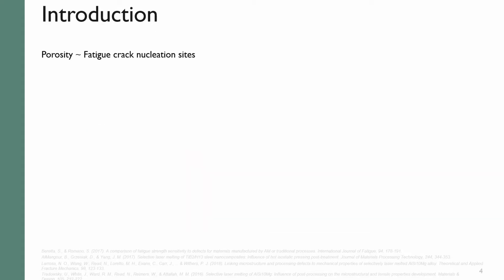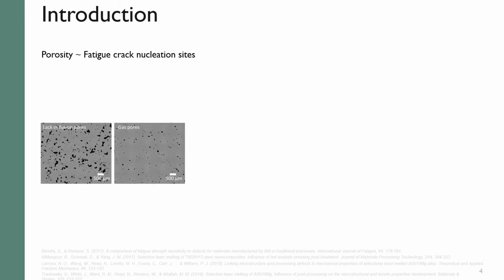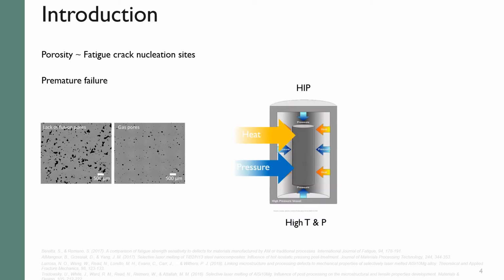However, as you all know, pores such as lack of fusion pores or gas pores are common process-related defects in LPBF parts, which can be detrimental to fatigue life, as the pores would act as crack nucleation sites and lead to premature failure. And therefore, HIP is commonly used as a post-processing for critical parts to improve density.